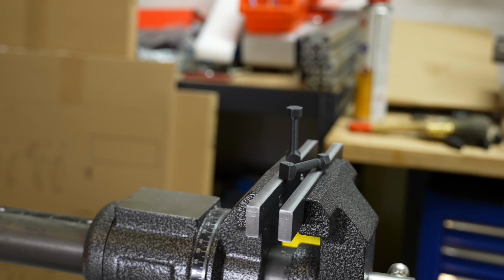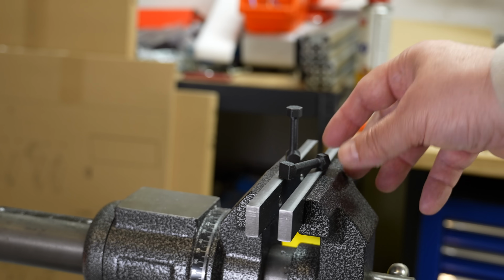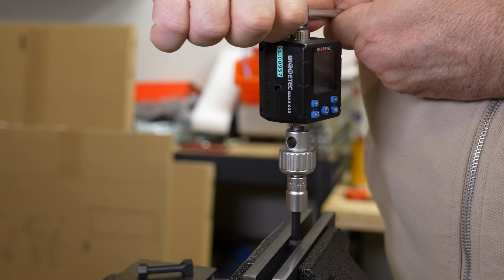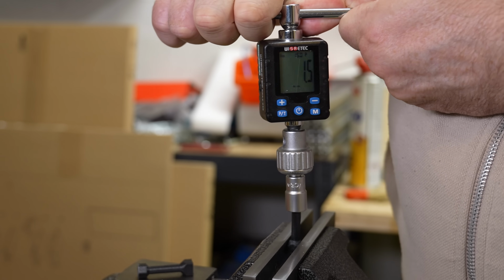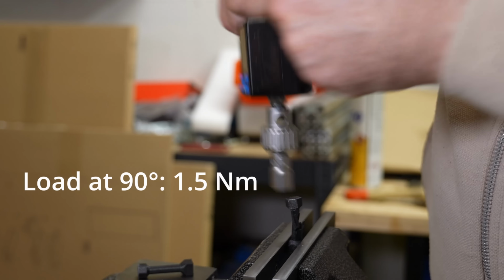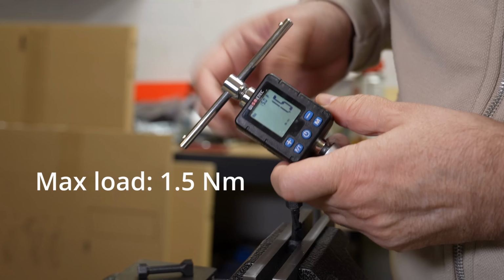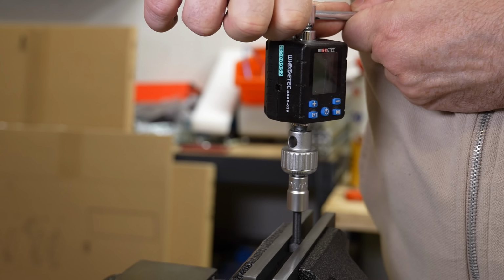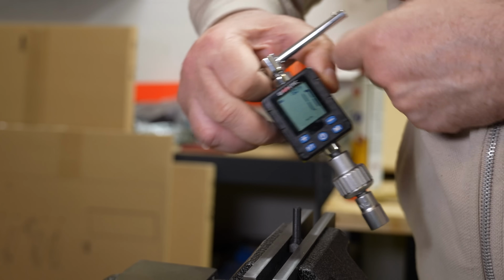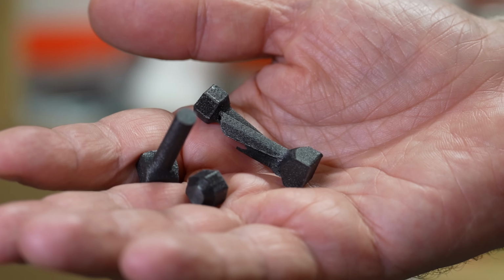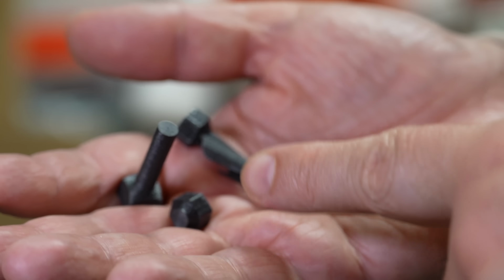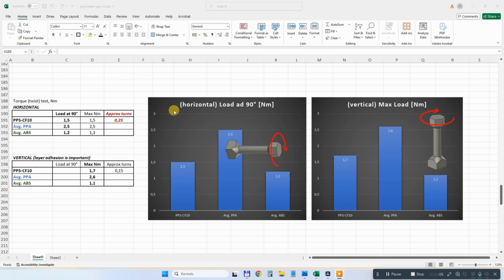The torque or twist test with horizontally and vertically printed test objects, and I'm starting with the horizontal one. 1.5 at 90 degrees. Printed in vertical position. 1.7. And again similar break loads, but this one printed vertically breaks more suddenly. For me the load at 90-degree rotation is more important, and here it is between these two materials but closer to the ABS. Printed in vertical position, it is somewhere between these two, closer to the average value.